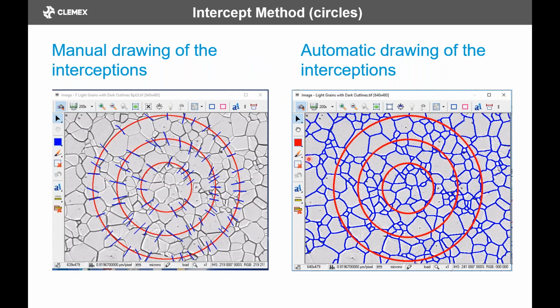Here's the intercept method that you could do from image analysis. If you have a structure that is very poorly defined, where we don't see the boundaries, or it's difficult to see twin grains, you could use the circles like this, and you just count the intercepts, right? Same principle as we just saw earlier, but the measurement will be done by image analysis, so everything will be counted. Once you're done, you have a number. Another benefit is that you can work at a different magnification. As you can see here, we have a 200x grain, so we're not limited by magnification in our calculation.